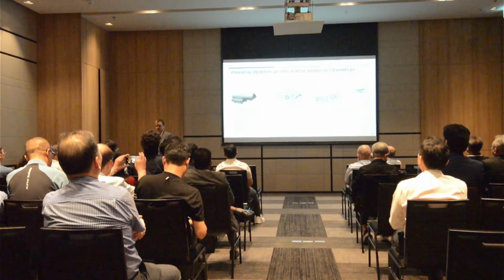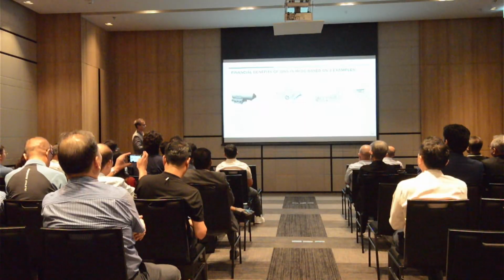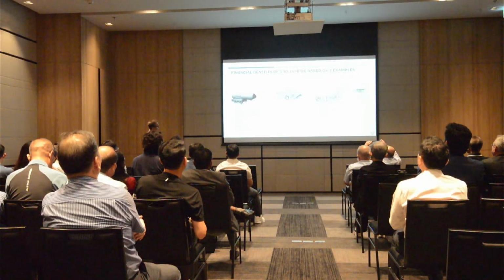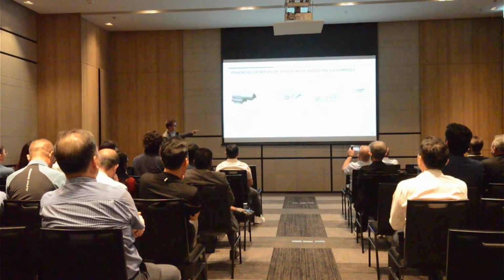Then in the middle we have a heatsink, a typical component which is already optimized in die casting, so good cycle time. The shot weight, or the part weight, is about 800 gram. It is produced on a 400-ton single cavity. Also here the calculation was 100,000 shots. And the cycle time was the same as the one on the left.